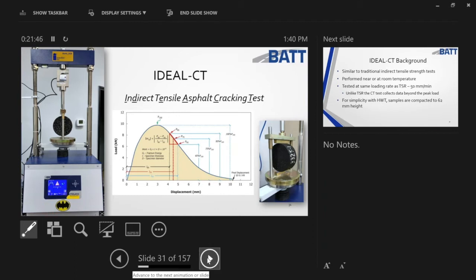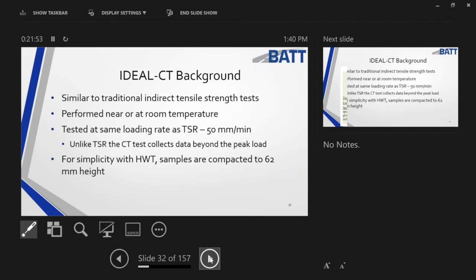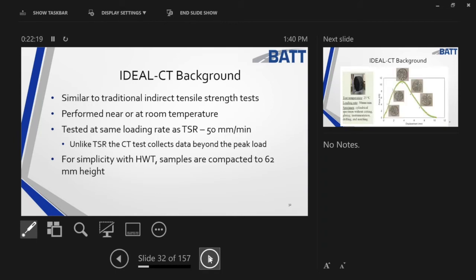So this test is one that a lot of folks are moving forward with. Now, if I look at the SCB, it does the same thing, the same type of curve that you're going to see, and just a different specimen setup. If I begin to look at the background, I'm going to focus here just on ideal CT. Again, similar to the indirect tension test that we're using, but unlike the TSR, we're going to go beyond the peak load with this. Still moving at 50 millimeters a minute, and for simplicity, we're just using samples that are compacted to 62 millimeters in height.